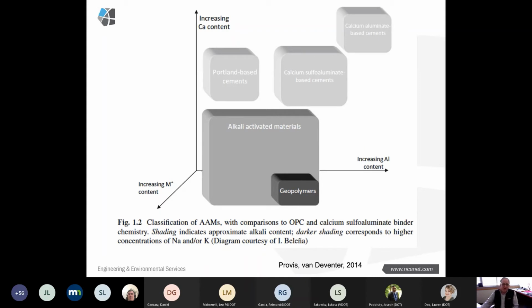So basically, an alkali activated cement tends to be a lower calcium cement that chemically reacts with the alkalis to form a hardened material. A geopolymer is a low calcium, high aluminum material that interacts with the alkalis to form a material. And then the Portland-based cement, the calcium sulfoaluminate cements, and the calcium aluminate cements are cements that are higher in calcium and react with water to form reactions. So they're not reacting with the alkalis, they're reacting with the water. So again, it's probably more chemistry than most people would want to get into, but this is kind of the space that we're living in. And right now, this alkali activated material and geopolymers is something that's getting a lot of attention.